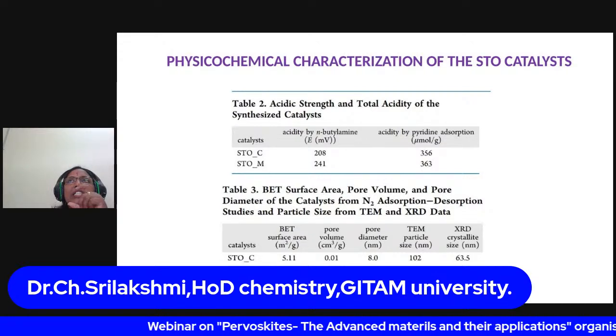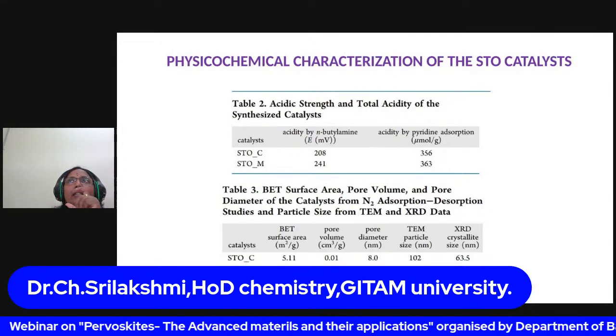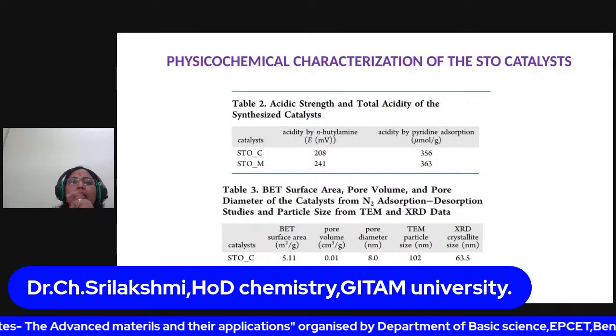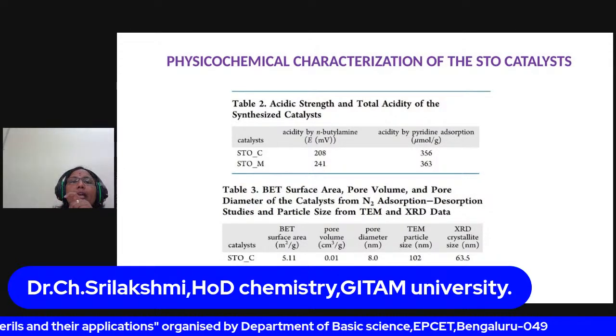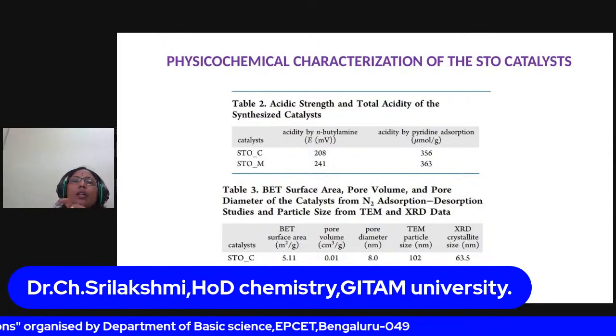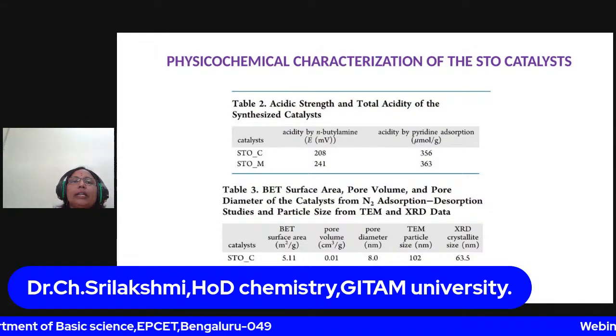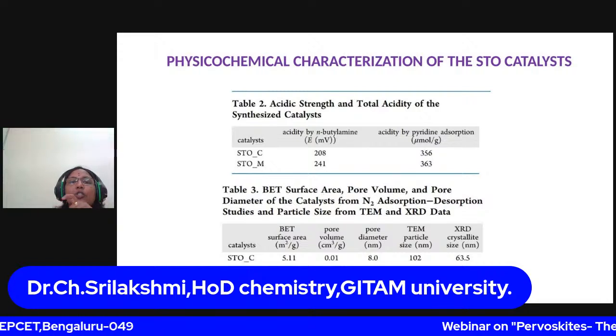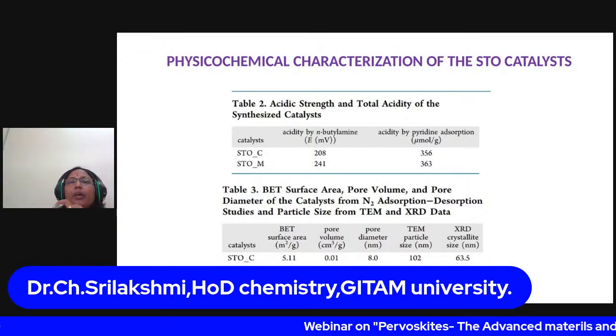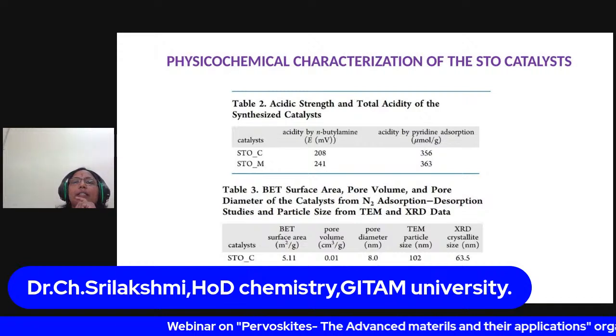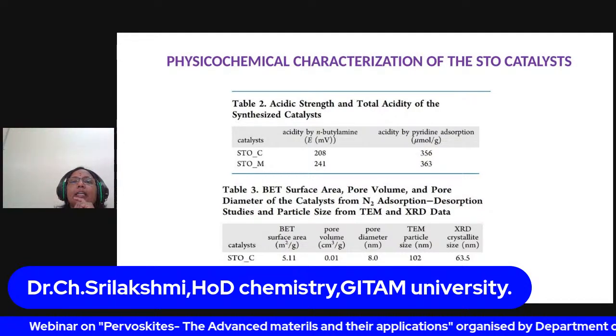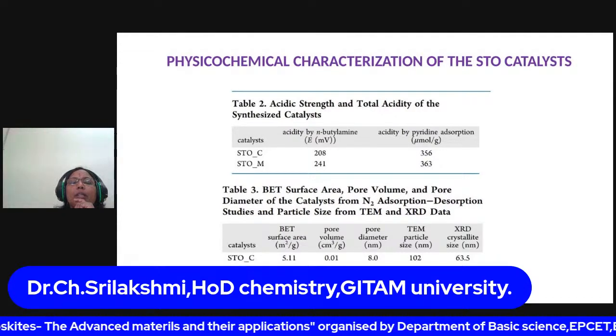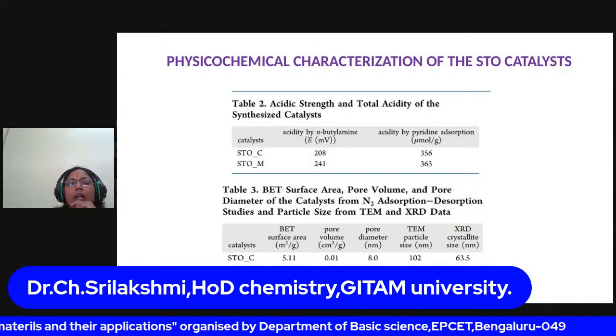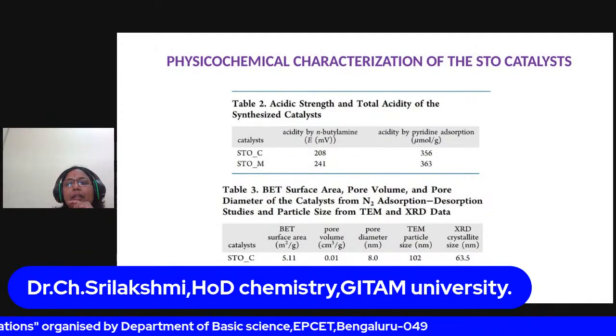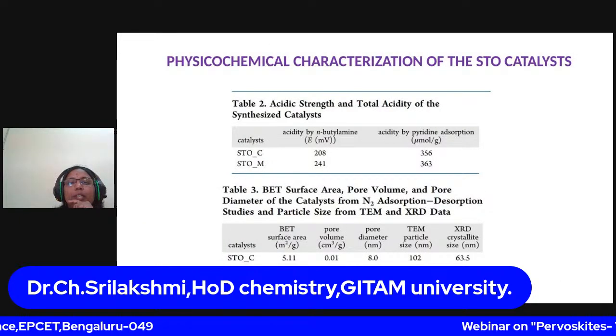If the initial electrode potential is greater than 100 millivolts, then the material contains very strong acid sites. Both materials show above 100 millivolts, so both are strong, but compared to the conventional catalyst, the microwave-synthesized catalyst has the strongest acid sites. Both contain Lewis acids, but the total acidity is higher in the microwave-synthesized catalyst compared to the conventional one. Now the BET surface area, which is very important.